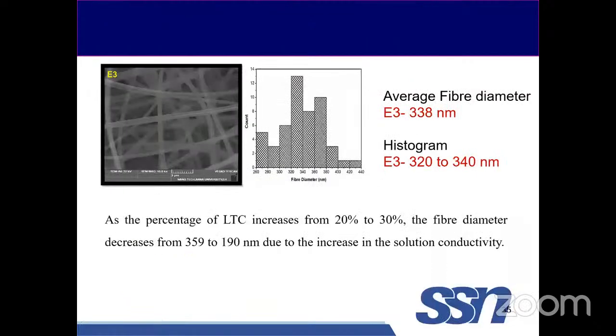For 30% LTC, the average is about 338, and the range is between 320 to 340. From this SEM image, we observed that as the percentage of LTC increases from 20 to 30, the fiber diameter decreases from 360 to 190 nanometers because of the increase in the conductivity of the solution due to the increase in the TiO2. But when we increase from 30 to 40, again the fiber diameter increases. This is due to the aggregation or agglomeration of the nanoparticles that we added, right?